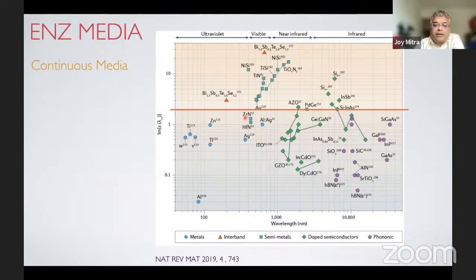Okay. Now, what is worth remembering is that even though the real part of epsilon goes to zero, the imaginary part of epsilon in all these materials is not zero; it has a finite value. And that's what gives a limiting parameter in actually realizing whatever I spoke about in the first view graph. Typically what we see is that if the imaginary part of epsilon is restricted to around 1 to 2 or below, that is where we actually get the goodies of ENZ materials.